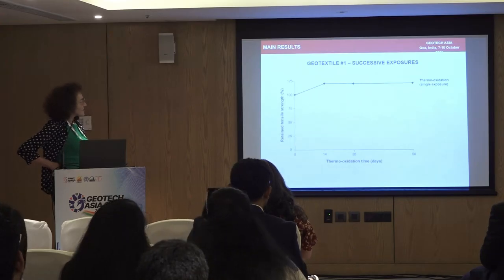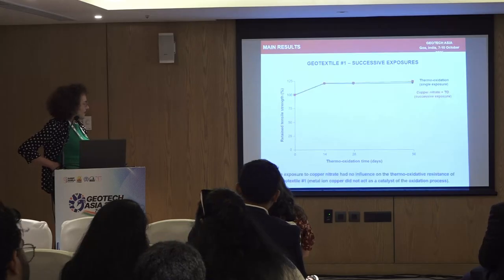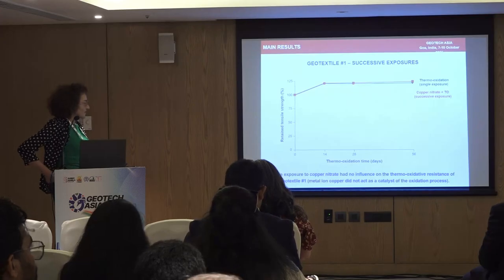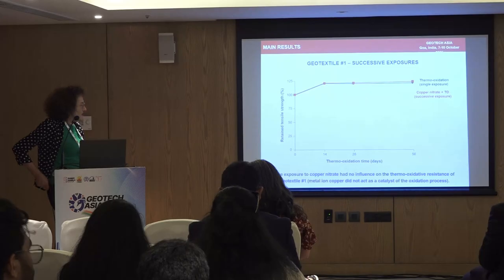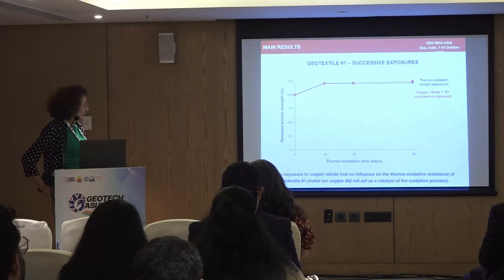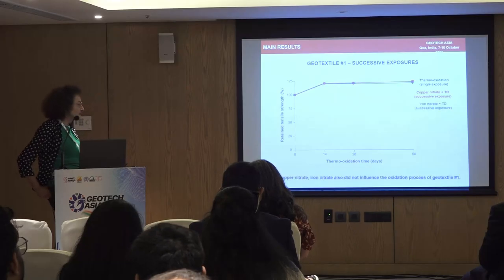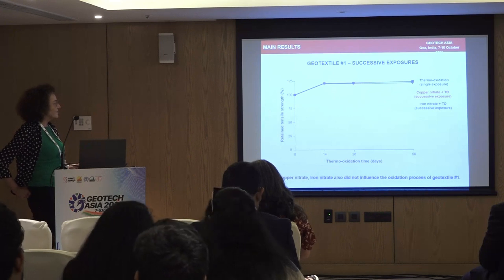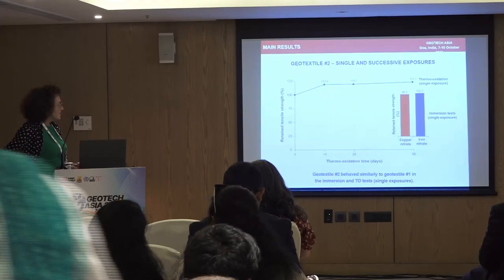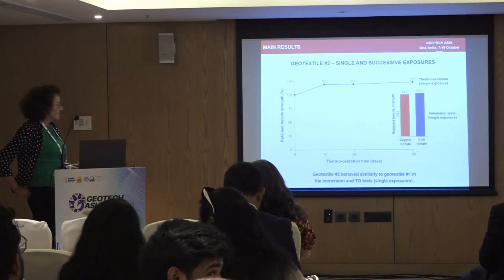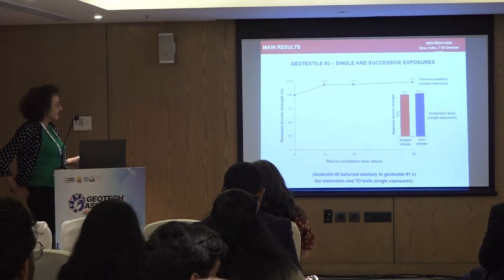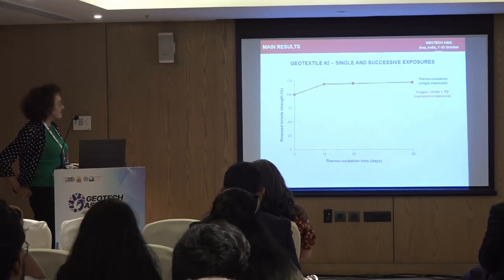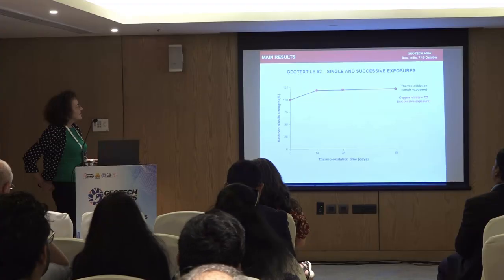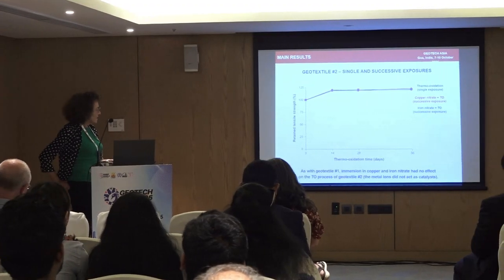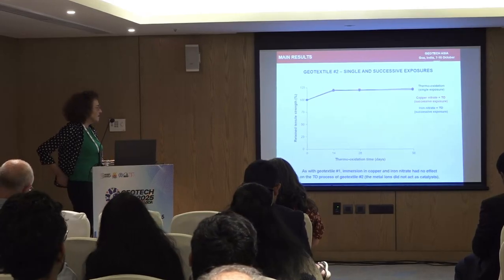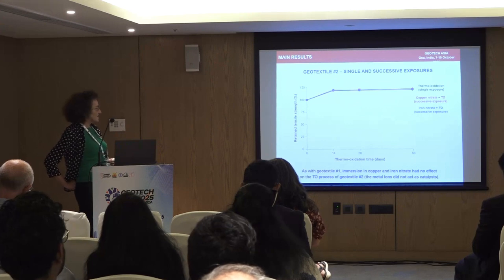In successive exposures, we see that the copper nitrate had no influence on the thermo-oxidation resistance, and iron nitrate also did not influence the oxidation process of geotextile 1. For geotextile 2, we have similar behavior when we did the immersion followed by the thermo-oxidation tests. In the case of geotextile 2, single and successive exposure, we see similar behavior as for geotextile 1,